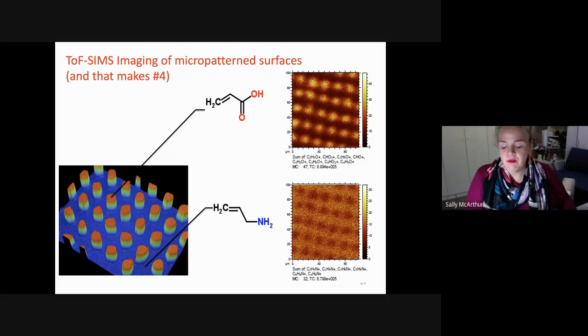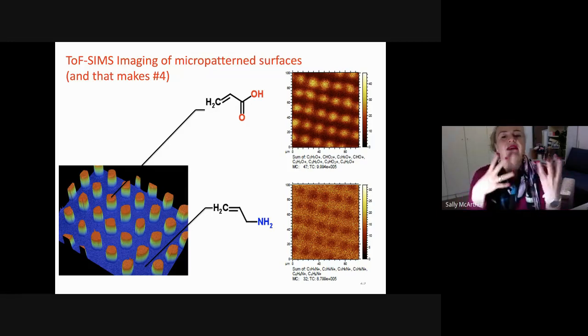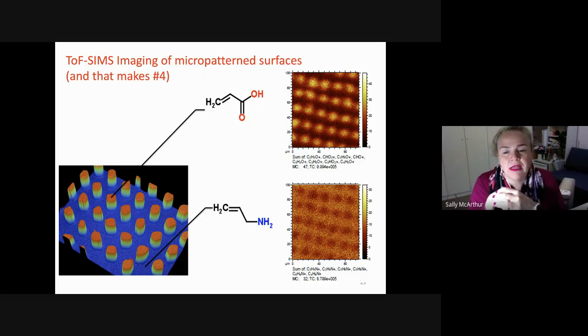Excellent. Okay, so I'll round up with this final take on some TOF-SIMS imaging. Here, what we're looking at is using that micropattern surface. We've put the micropatterning technique to work and created micropatterns of the amine and acid surface with a 10 micrometer pattern. These aren't particularly high resolution images. They're actually more focused on the